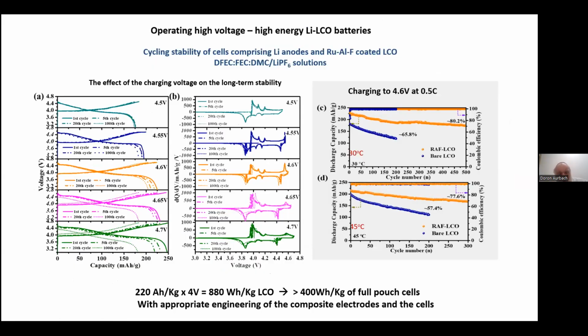Now going further, the question is how far we can charge. So we did different experiments. We even charged up to 4.7 volts, but then we realized that we can charge up to 4.6 volts. We can get 220 milliampere hour per gram. And this is very important, because we have 220 ampere hour per kilogram times 4 volts. So we have 880 watt hour per kilogram for LCO, just the cathode.